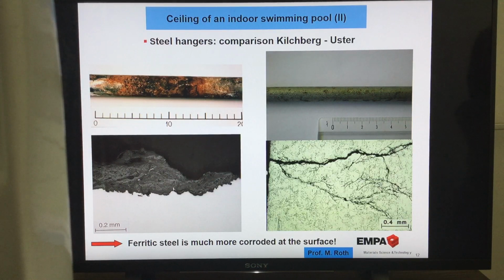Look, very nice to see again the two cases. Here the Uster case, you remember that steel bar. From the outside it looks not that bad. All these small pits just, and the inside from the pit, the cracks, they are dangerous. It was totally cracked. And here, from the outside, it looks very crazy, very much heavily corroded. Then we make the microsection and we see here the corrosion layer, and underneath in the base material, no cracks. So here no cracks and here cracks. That's a big difference. And again, the story, this is a much cheaper material compared to that.